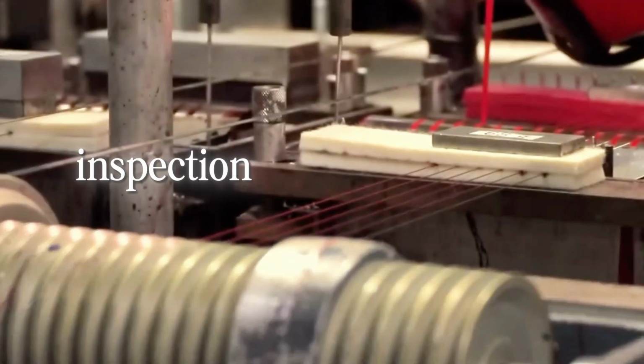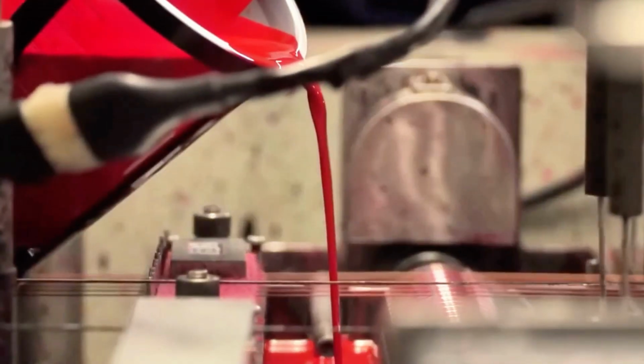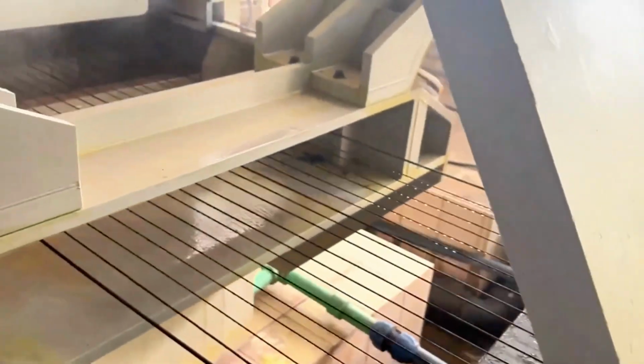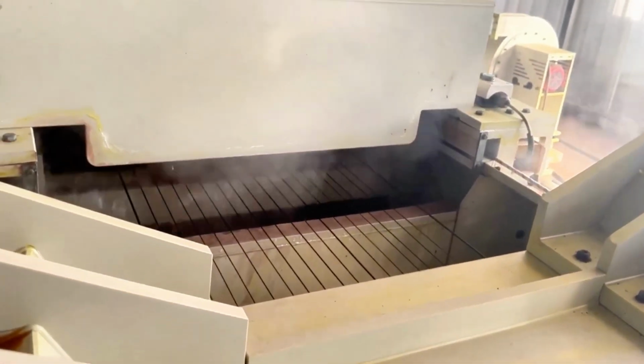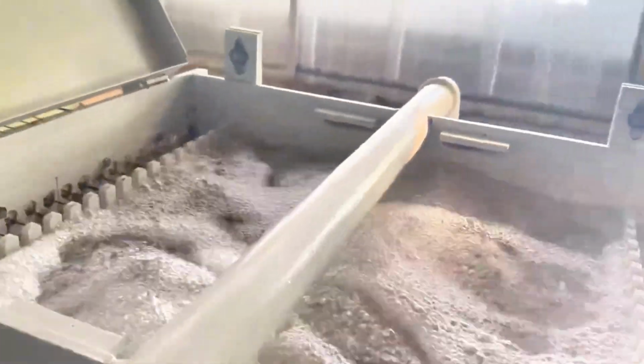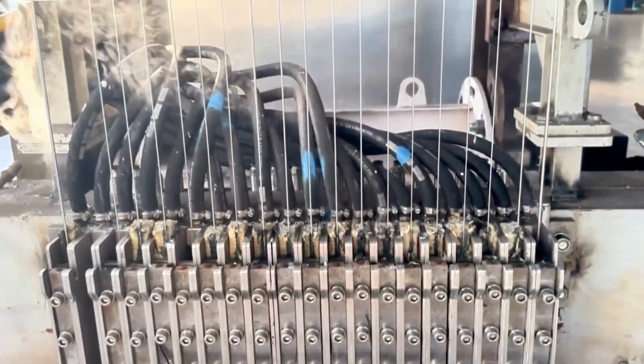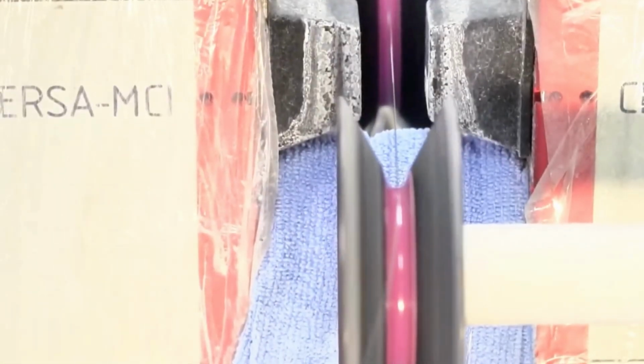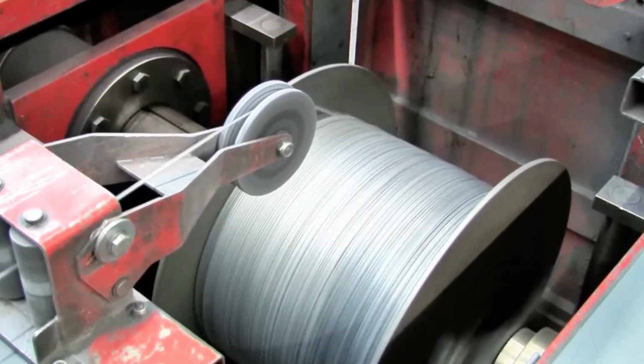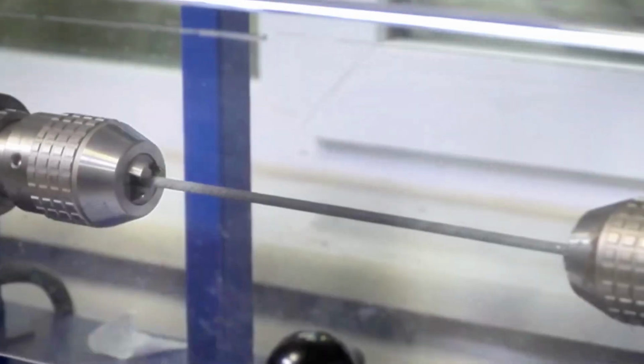Step 9. Testing the limits, inspection and quality control. Once coated, every wire faces its moment of truth. In the inspection hall, advanced equipment checks each coil against precise specifications. The diameter must be exact down to thousandths of an inch, and the surface must be flawless. No bends, no scratches, no microscopic cracks. Some tests are non-destructive, using ultrasonic waves to look deep inside the wire for hidden voids or weaknesses. Others are brutal. Tensile machines stretch samples until they finally snap, revealing their breaking strength.